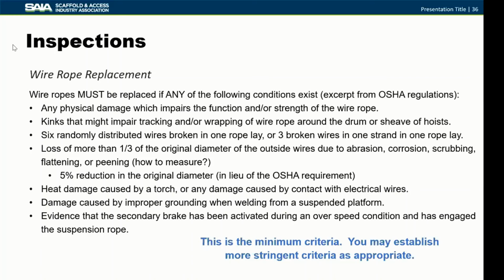The loss of, what OSHA says is the loss of more than 1/3 of the original diameter of the outside wires. That's pretty tough to measure. I'm not exactly sure how somebody in the field would measure that. So I think probably the proper approach here is to use a preset reduction in the original diameter. We specify a 5% reduction in the original diameter, that is when the wire rope should be replaced.